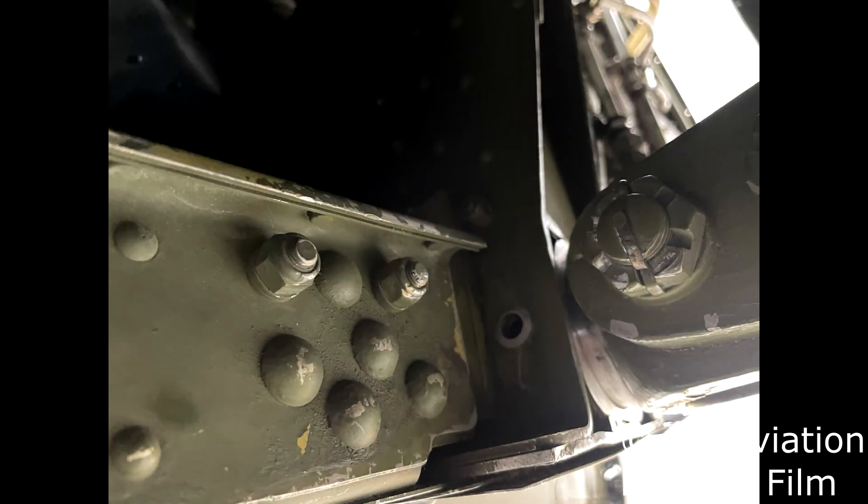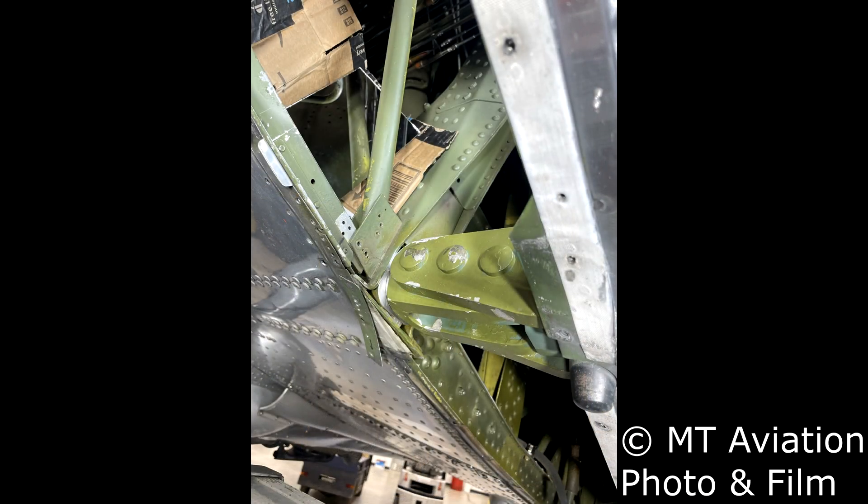The terminal is made up of steel and slides into an outer aluminum piece which then mounts to the aluminum shear web wing structure. Although it is held by multiple bolts, only the inboard-most bolt hole is of concern because if a crack forms there, the end of the terminal could completely shear off, separating the wing from the fuselage. In theory, if there was an issue with any of the other bolt holes, the terminal would still have bolts downstream of the defect hole holding it in place.